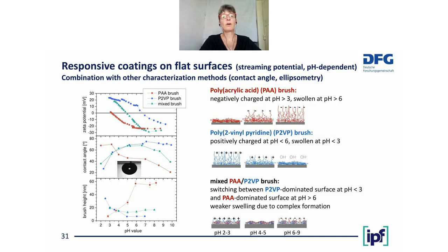Another example of polymer or polyelectrolyte brushes are responsive coatings. In this case, we compare 3 different kinds of brushes: an acidic brush, polyacrylic acid brush that has the property that it is collapsed at low pH value and swells at high pH value. The poly-2-vinyl pyridine brush is an alkaline brush. It has the opposite behavior. It's swollen at low pH and collapsed at high pH value.